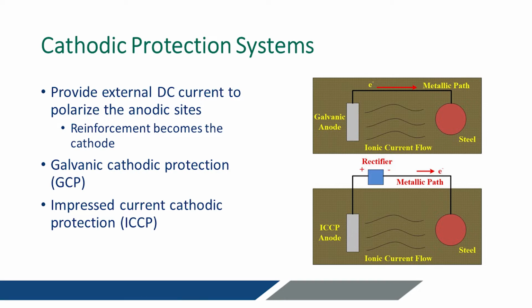For the areas that are delaminated now, that's just concrete repair. We need to remove that concrete, clean that steel, and put the concrete back. But the areas that will be corroding in the future, that's really what my talk is about. What are we going to do to mitigate that before it starts? We're not going to chip out that good concrete now to prevent it in the future. What we're going to do is apply cathodic protection to stop that corrosion before it starts.